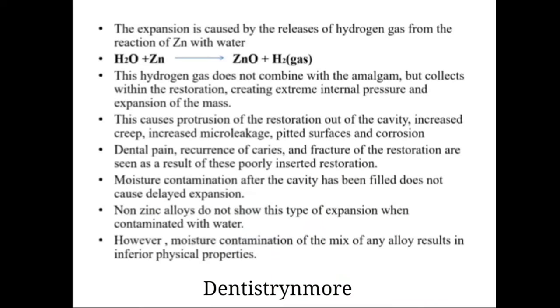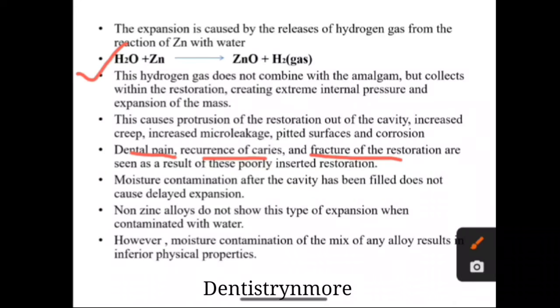And here you can see the reaction. The expansion is caused by release of hydrogen gas by the reaction of zinc plus water. This may cause various symptoms like dental pain, recurrence of caries, and fracture of the restoration may occur. Moisture contamination after the cavity has been filled does not cause delayed expansion. Non-zinc alloys do not show this type of expansion when contaminated with water.